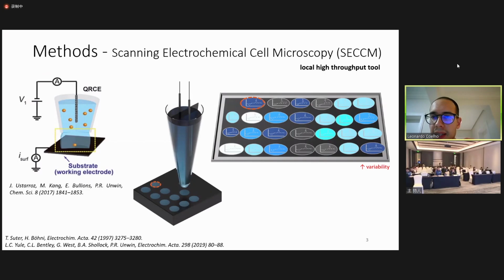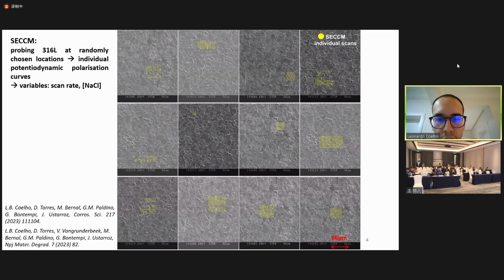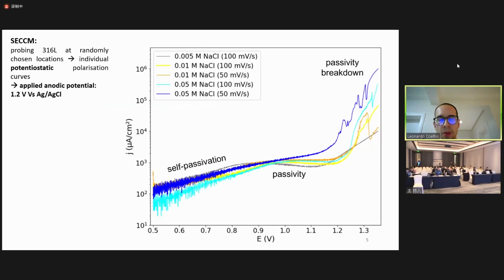This is a droplet-based technique, so you should realize that each one of those individual footprints left on the surface has about 1 micron of dimension. So we have varied the scan rate of the potentiodynamic polarization and also the chloride concentration, which is related to the aggressiveness of the corrosion test. And after that, in this study in which we varied, as I mentioned, the chloride concentration and the scan rates, we were able to obtain those types of curves.